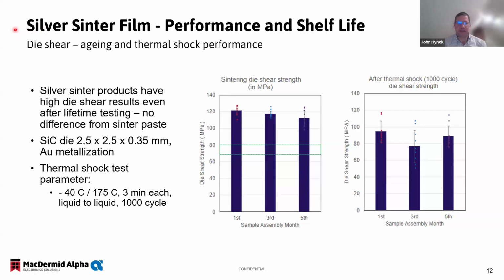All right. I had mentioned in an earlier slide that we have data that shows there's no difference in performance over lifetime. So that's what I wanted to show here. What we did is we've been aging this material and then doing shear tests after aging. And the die we're using is a 2.5 by 2.5 millimeter die with gold metallization. And we sinter it, and what you can see here is there's really no difference in the die shear between the first month and the 5th month of storage. And even after thermal shock, the die shear strength still holds up really, really well.